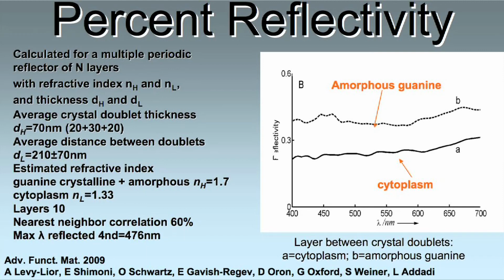And in fact, if we simulate the reflectivity based on cytoplasm in the middle between the crystal doublets, we obtain a pretty lousy combination. But if we use the index of refraction of the amorphous guanine, the reflectivity is much higher. So taking into account the whole thing, the spiders succeed in getting a reflectivity of up to 40% that is uniform over the visible spectrum, and it is in all directions, because in fact, light in the spider comes from all possible directions and not as in the fish, only from one direction. So this explains why they are less ordered.